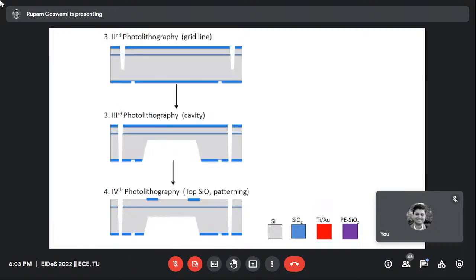Next slide, please. So once we have this kind of thing, whatever process we have defined is to reduce the thickness of the top layer, because we wanted 1 micron thick and it was 2 micron thick. So we had a process to remove the layer so that it is 1 micron everywhere. And after that, we have the process of making the cavity from the backside, and in this case again we have used the TMAH process.